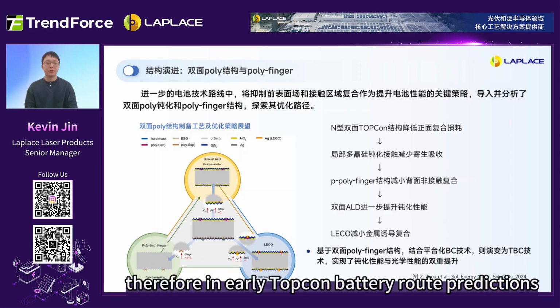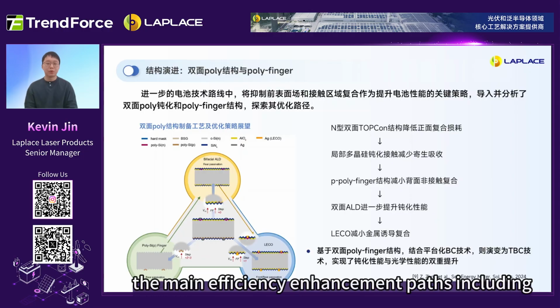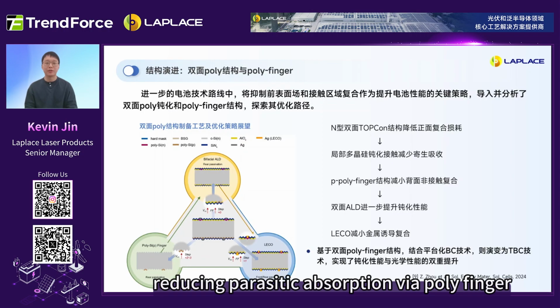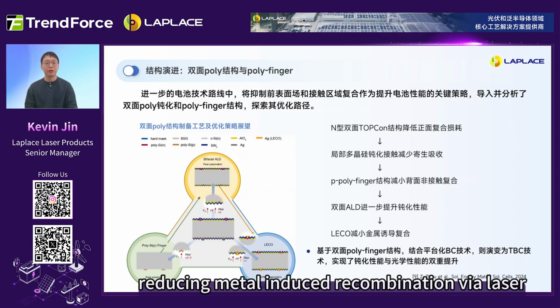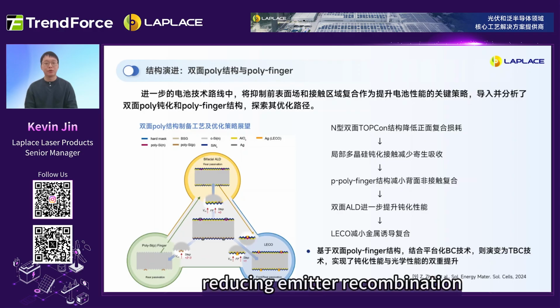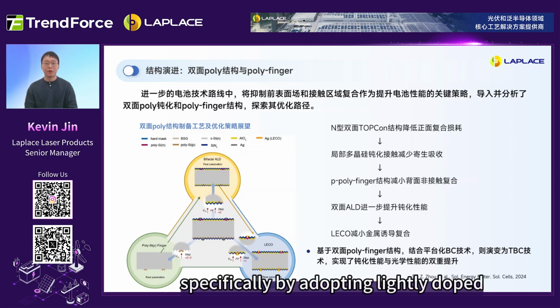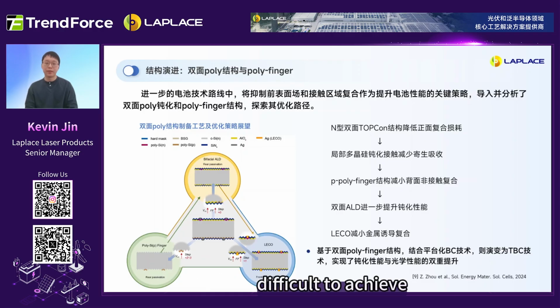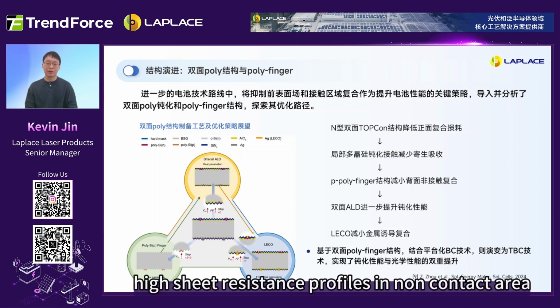Therefore, in early TOPCon battery route predictions, the main efficiency enhancement paths included reducing parasitic absorption via polyfinger, reducing metal-induced recombination via laser SE, and reducing emitter recombination, specifically by adopting lightly doped, difficult-to-achieve, high sheet resistance profiles in non-contact areas.